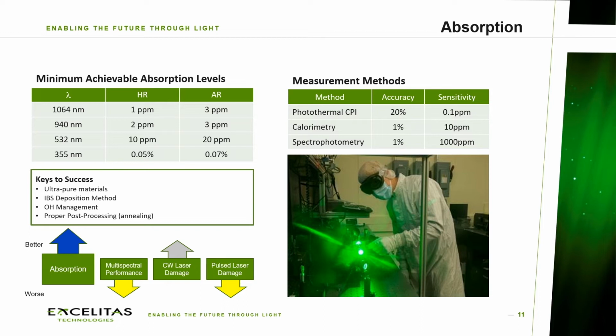Now, when we're optimizing absorption, we need to obviously maintain high purity of the materials. We're typically using ion beam sputtering. That's where we can get these absorption levels that are down around 1 part per million. We have to be careful about OH, water content of the various materials, and we have to think about how we're going to post-process the materials. When we do all this, we will see the absorption improve.